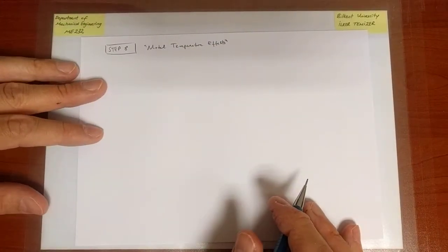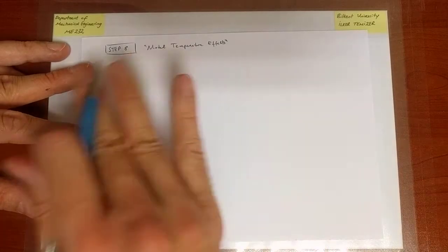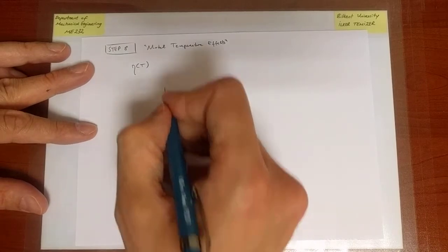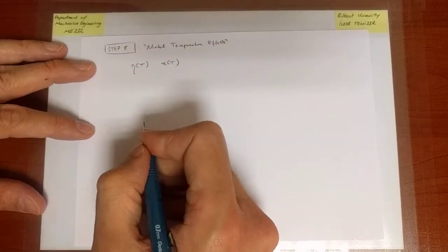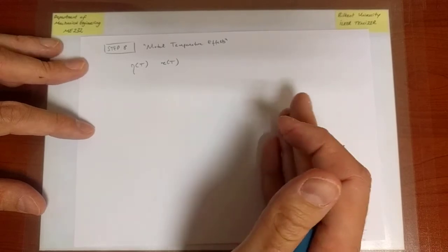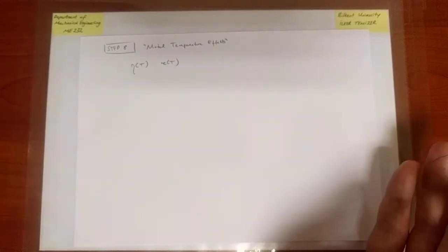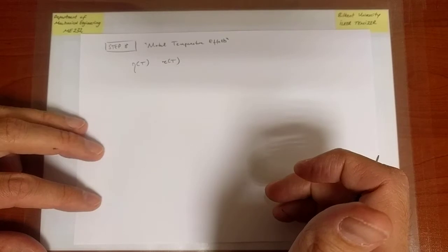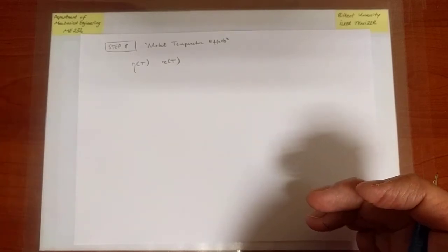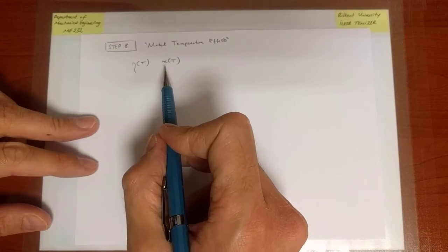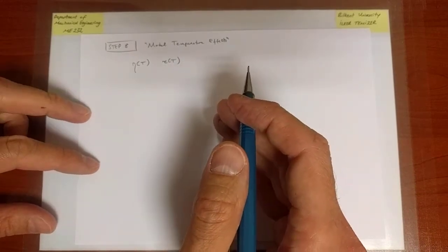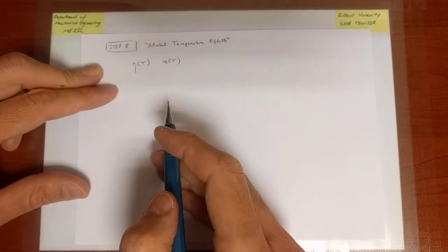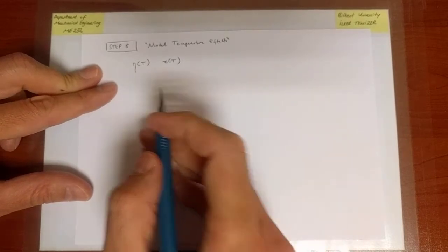And there are a number of key observations that we've already stated which are going to guide that model. First of all, what we've observed is that the viscosity is a function of the temperature, and so is therefore the relaxation time. The elastic moduli that appear in our model, such as E and E infinity, if the polymer is well modeled by the standard linear solid (SLS) model, are the only two elastic properties that appear. We've said that those are approximated as not depending strongly on temperature. The viscosity eta and the relaxation time are therefore much more strongly dependent on temperature changes.